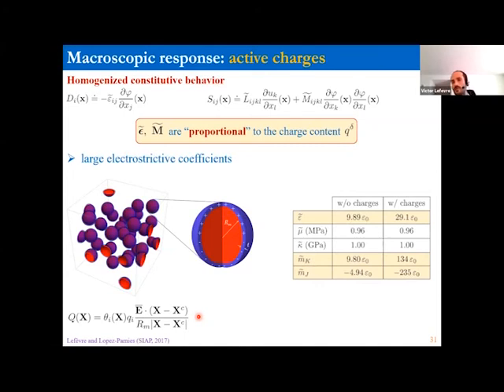And so in this table, we have a comparison between the behaviors of the composites, depending on whether they have space charges, so here on the right, and without space charges on the left. So for the permittivity, you see that if you have space charges, you enhance the permittivity by a factor of 3. The mechanics doesn't change, obviously. That's the shear modulus, bulk modulus, and the 2 electrostrictive coefficients. The first one is enhanced by a factor of 13, and the other one is enhanced by a factor of 45. There's really a significant, even drastic impact of the presence of space charges on the macroscopic elastic dielectric response of these materials.